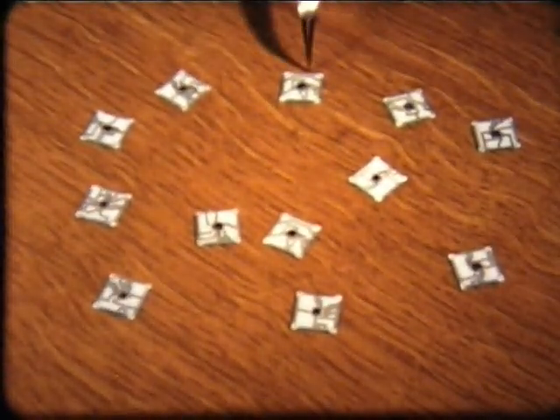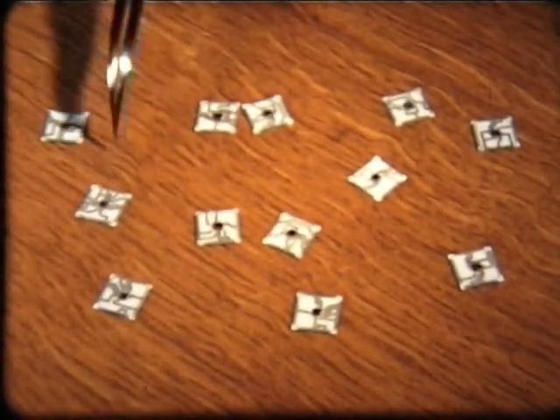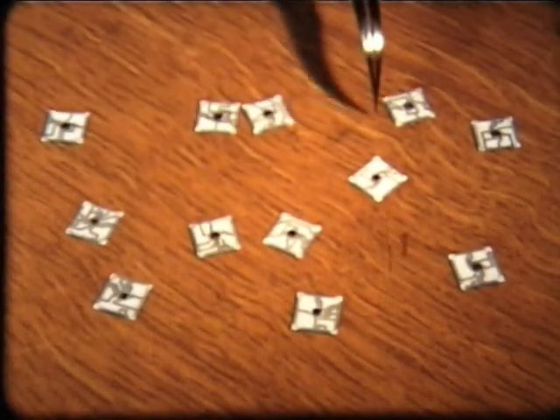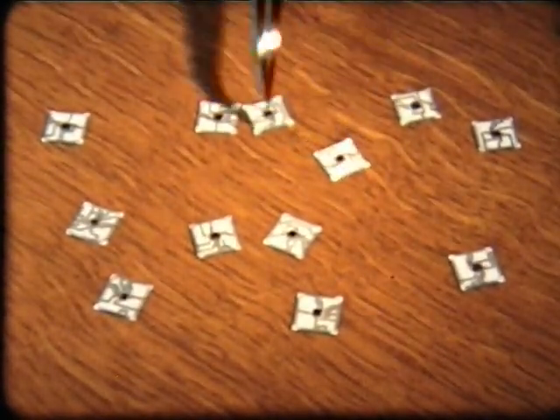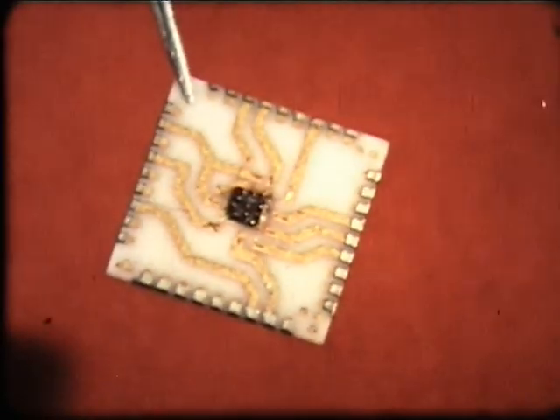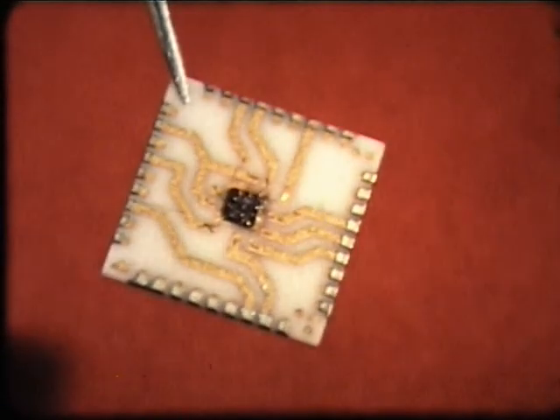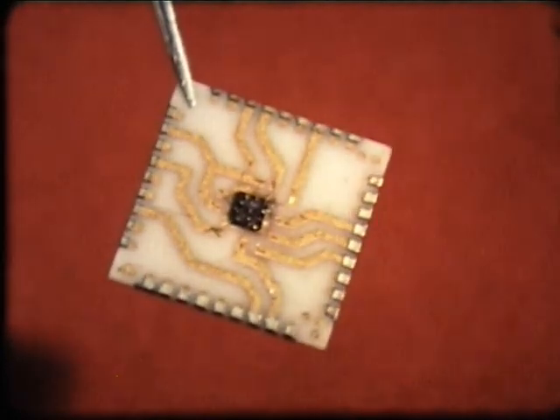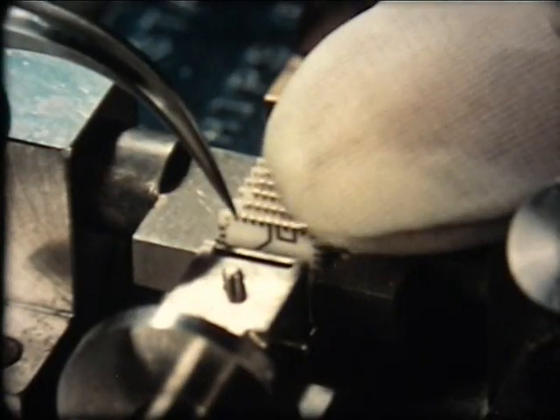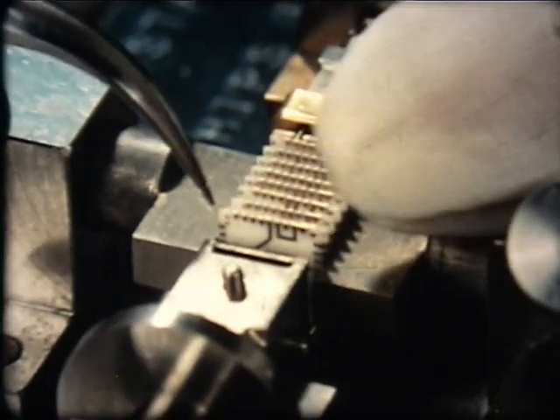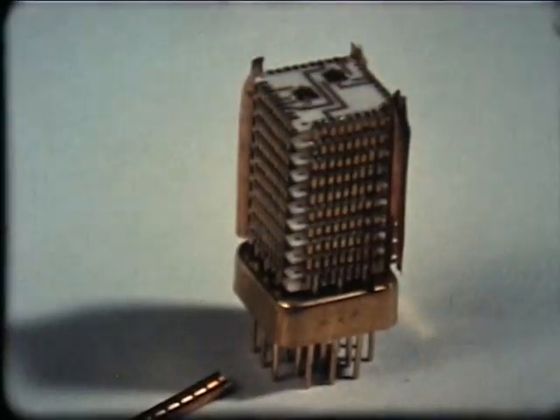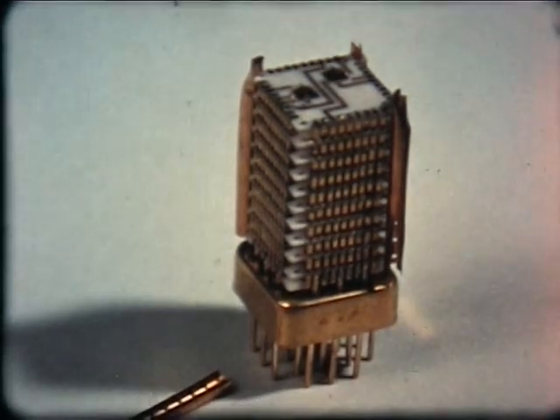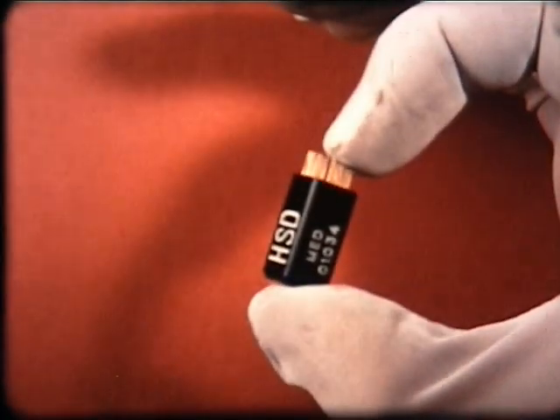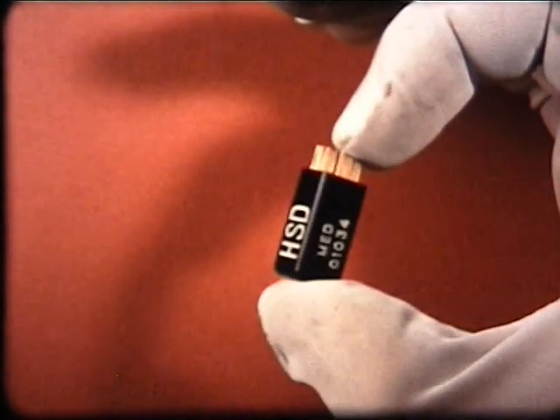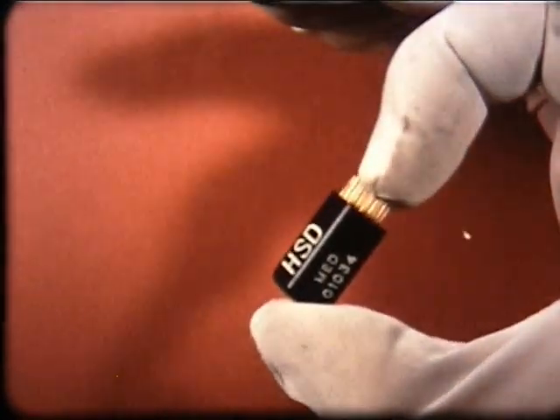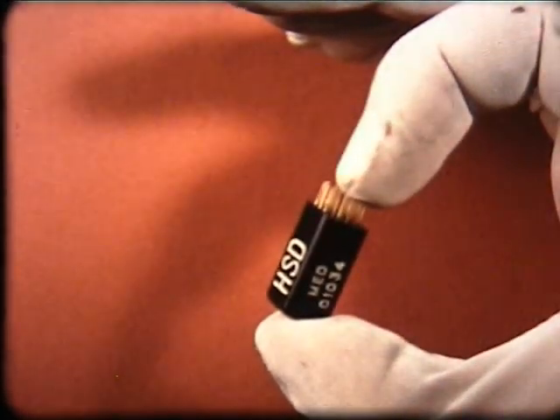Another micropacking process has been put into full production by Hawker Siddeley Dynamics. Silicon chips made at Gem Mill are mounted on ceramic wafers 8 mm square, with connections to vacuum-deposited conductive tracks leading to edge terminations. Up to 14 of these can be assembled in stack form. The edge terminations are wired up using a computer-controlled electron beam welding machine. The finished assembly in its hermetically sealed welded can is only 2 centimeters high and 1 centimeter square.